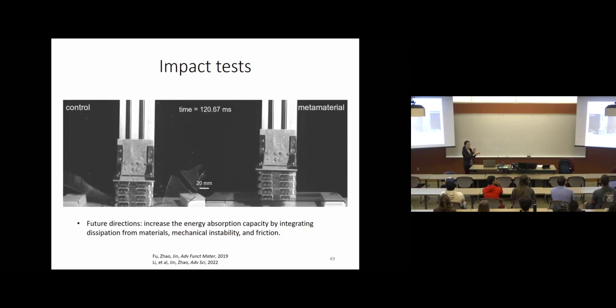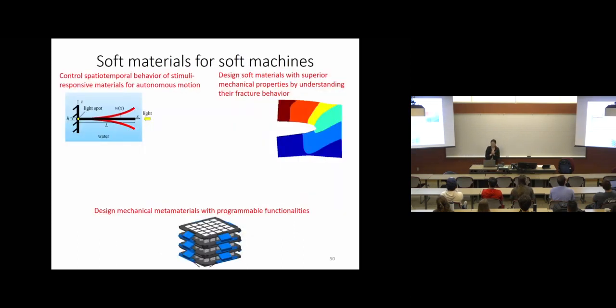If you pay attention to the input energy, so far those reusable materials are only capable of dissipating energy at a very, very low level, orders of magnitude lower compared to the traditional non-reusable energy absorbing materials. So our current efforts and future directions are to further increase the energy absorption capacity by integrating dissipation from different mechanisms: material, mechanical instability, and friction. I don't have much time to talk about this second literature here, but we have already designed some metamaterial which shows reusable energy absorption capacity at a similar level as the traditional non-reusable ones. So let me wrap up my talk.